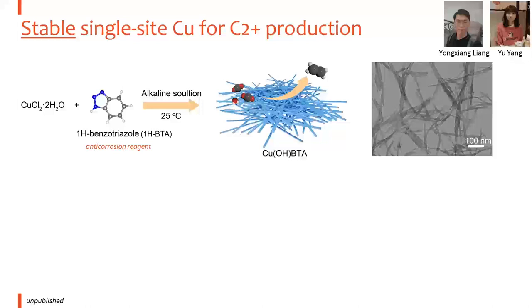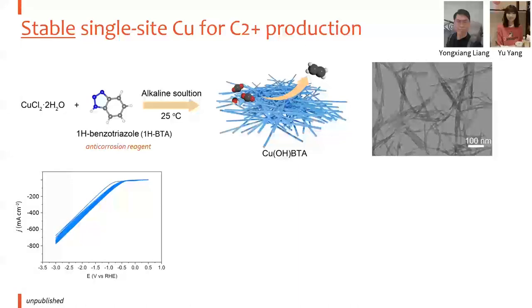So we synthesized this material, by Yu Xiang and Yu Yang, my PhD students. And actually the synthetic route is very easy. You just mix them together at room temperature and alkaline condition, and you will form this very nice nanowire morphology. So first we use electrochemical CV characterization for characterizing this material. We found that even under very negative applied potential and under very large current density, we cannot see the reduction peak of this material. Of course, we cannot see the corresponding oxidation peak of this material.